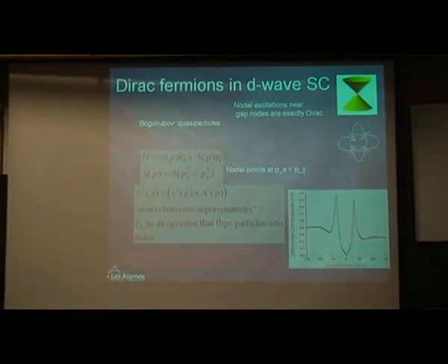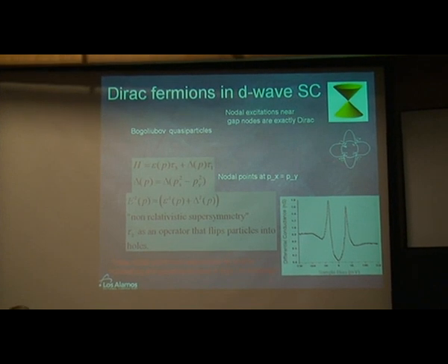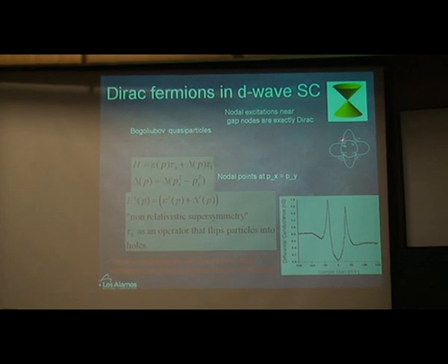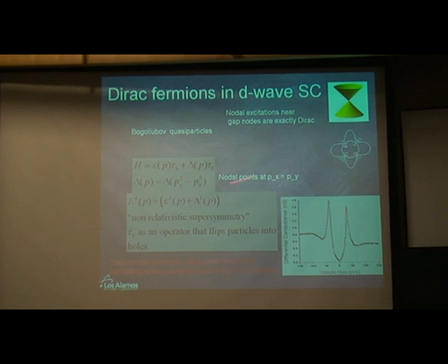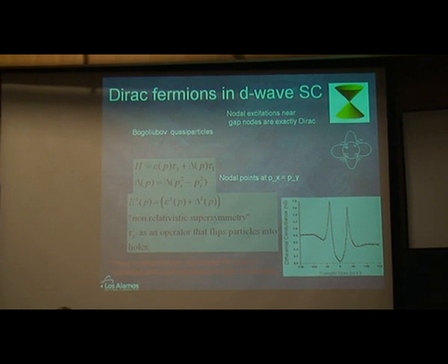So how this nodal structure comes about in the d-wave superconductor is very simple. If I have a Fermi surface, which I try to draw here as a circle, and I come in and open the collective gap or superconducting gap, which has a node at these 4 points. So for instance, if the gap vanishes as a function of momentum at the 4 points on the Fermi surface of p_x equal to p_y, then at the Fermi points, along the diagonal directions, I have essentially very few quasi-particles. And those quasi-particles are responsible for the phase space for excitation, filling up the gap and this V-shaped characteristic d-wave tunneling density of states in the case of the superconductor. All right? And like I said, these nodal points are responsible for all sorts of anomalies and physics in high Tc at low temperature.